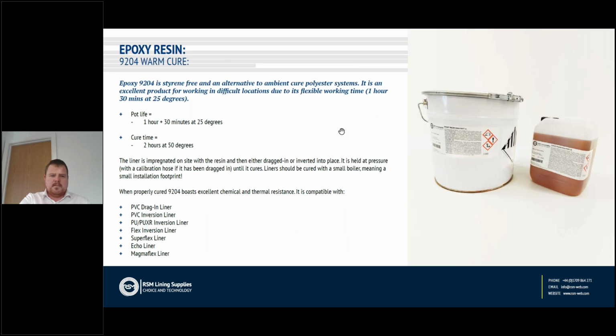Moving on to the sort of middle resin in our epoxy range, this is the 9204. It's a great alternative to polyester resin for liners that are sort of between ambient and hot cure, for example. So it has a pot life of around about 1 hour and 30 minutes at 25 degrees. That is increased significantly if we chill the resin down, and we can get 3 to 4 hours pot life at the lower temperatures with a very controlled cure of 2 hours at 50 degrees.